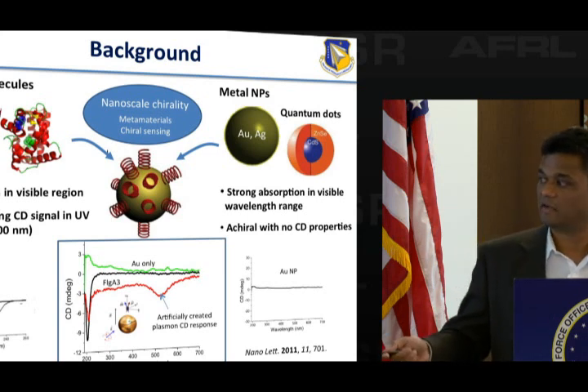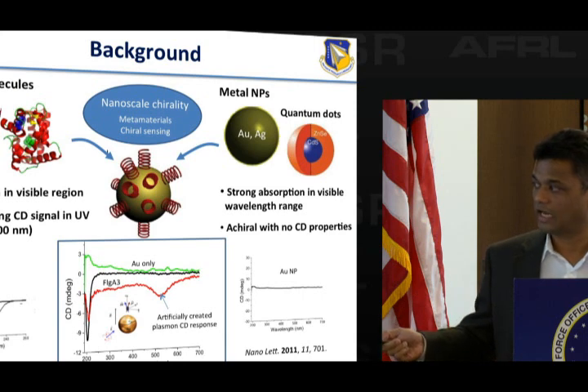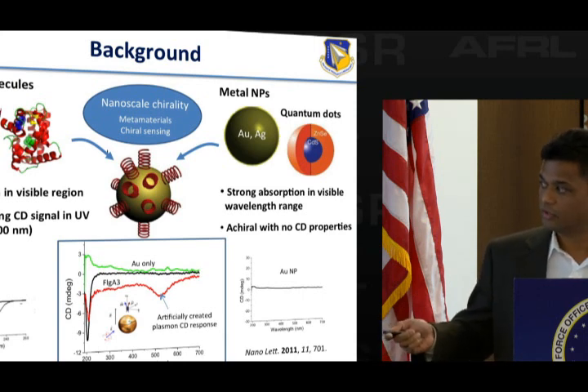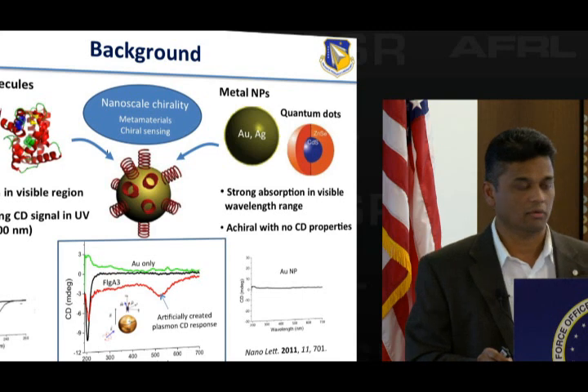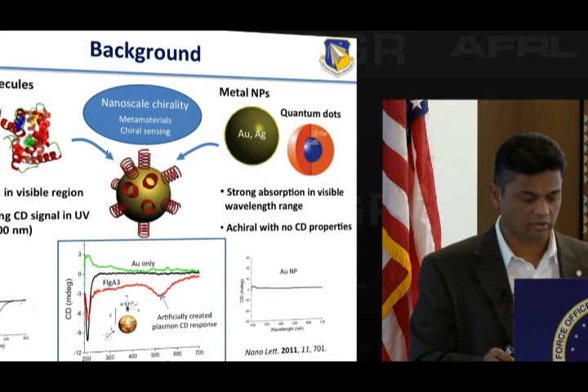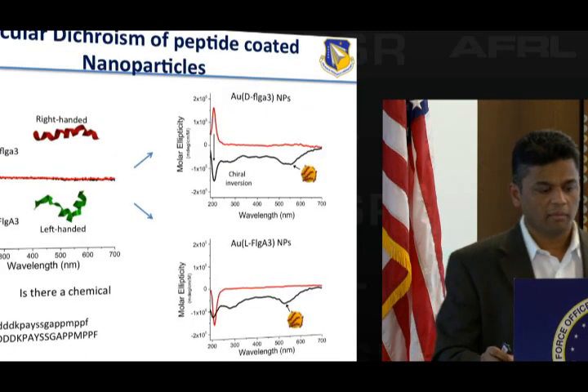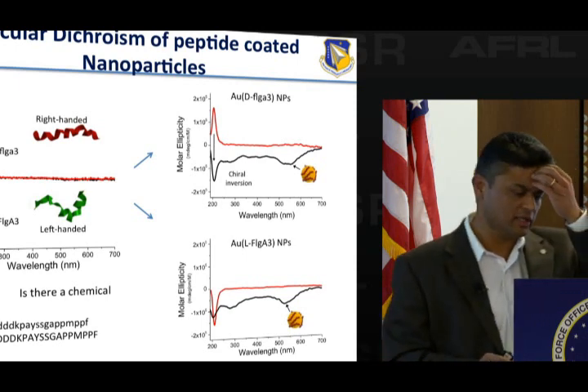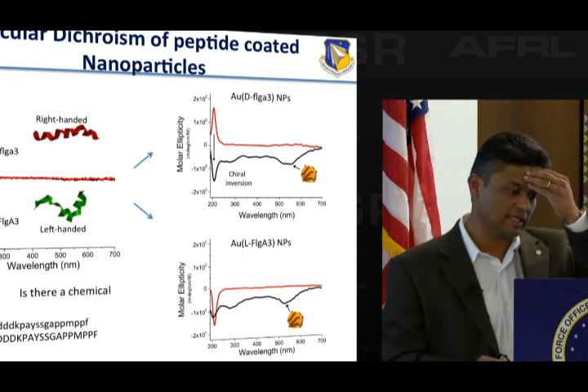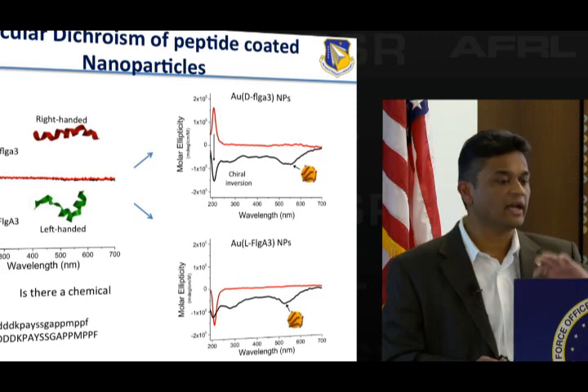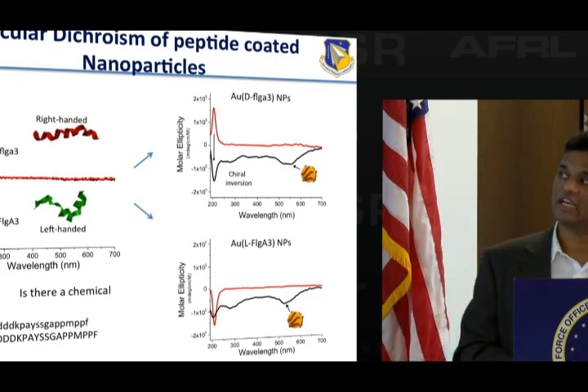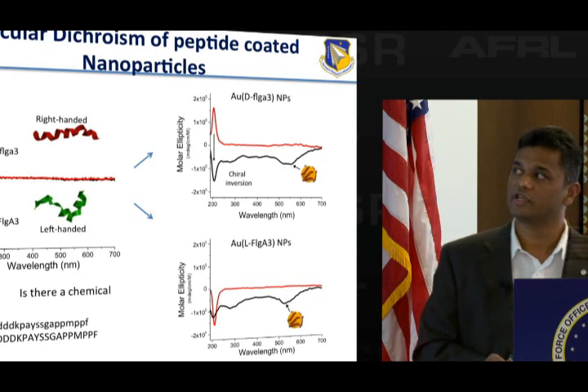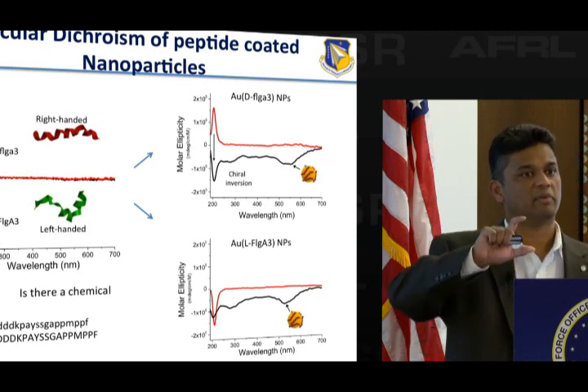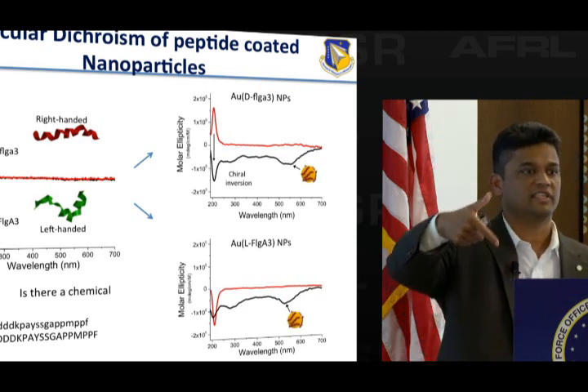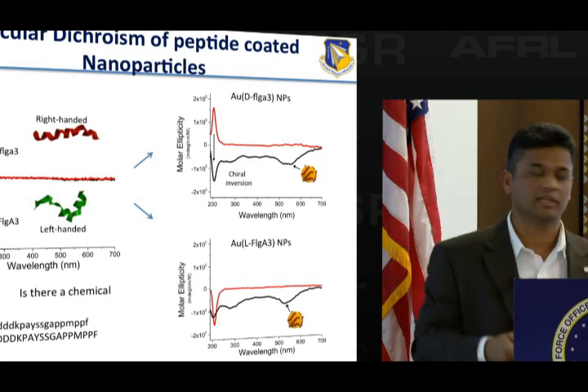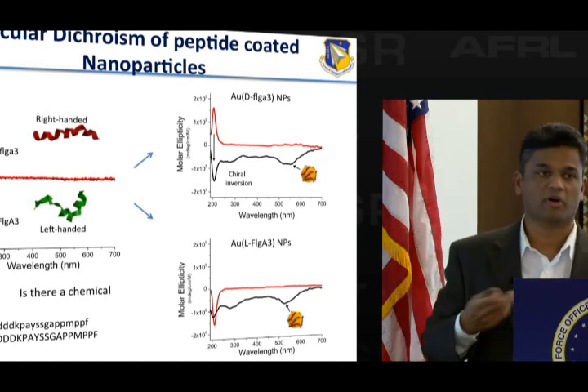Now, it's highly dependent: if I use a rod, the peak actually shifts. So you have two modes. You can actually get those modes to show up in the CD in the presence of the peptide. But what was interesting is I asked Joe Slocik, the scientist working on the project, I said, okay, we have left-handed and right-handed peptides. Let's do the experiment. If I use the right-handed peptide, will the surface plasmon resonance peak also flip? Because if it's just a simple interaction, you should just see a flip of that signal, and the surface plasmon should actually be on the positive side too.